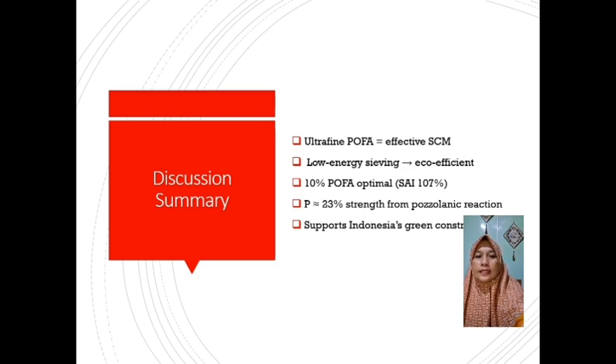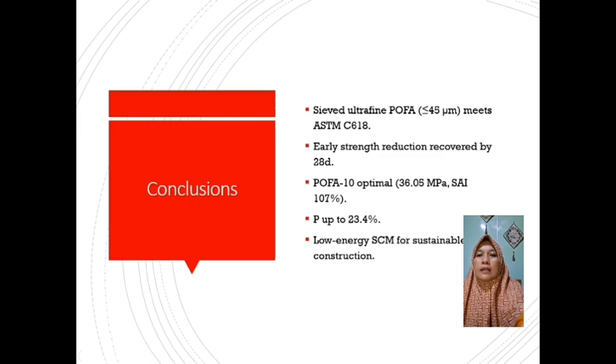To conclude this presentation, sieved ultrafine POFA lower than 45 micron meets ASTM C618 requirements. Early strength reduction is recovered by 28 days. 10% POFA achieves optimum performance with strength of 36.05 MPa and strength activity index of 107%. Pozzolanic contribution rises up to 23.4% at 90 days. This approach offers a low-energy, sustainable pathway, reducing cement consumption and also carbon dioxide emissions.